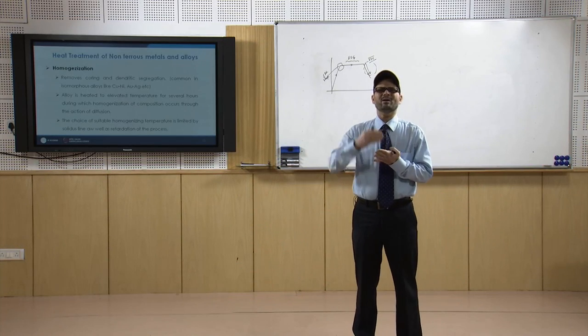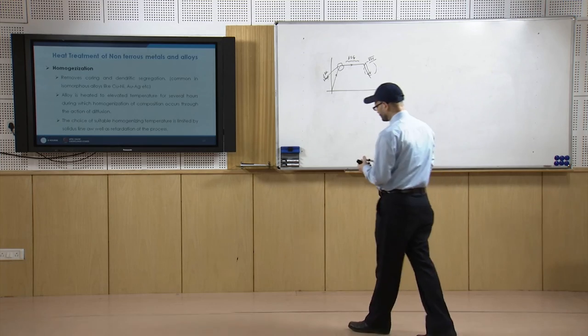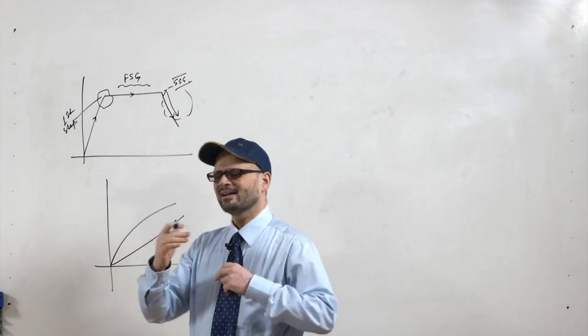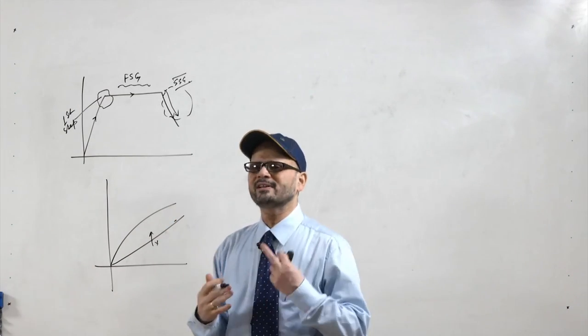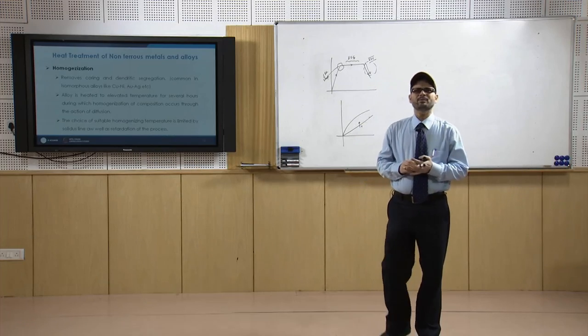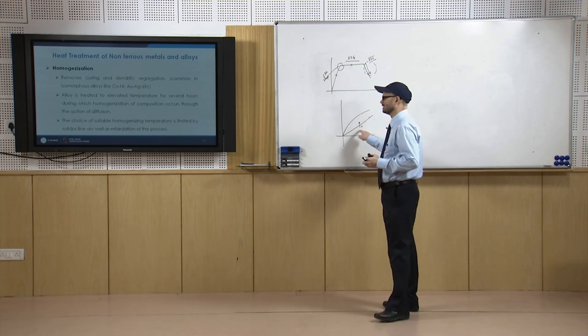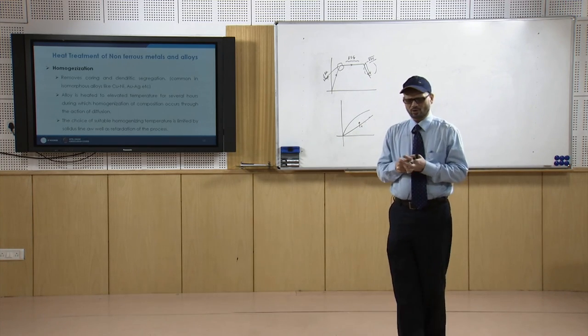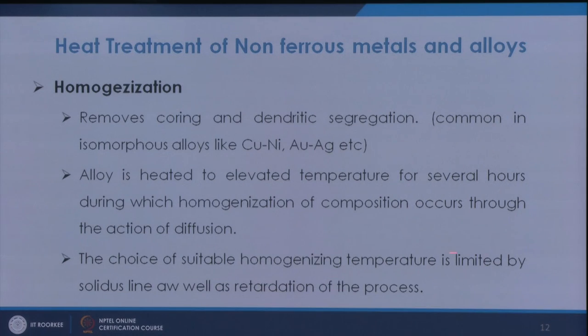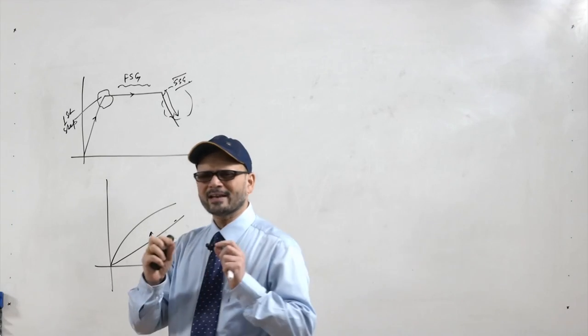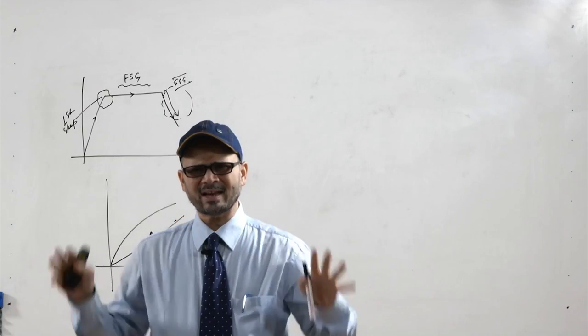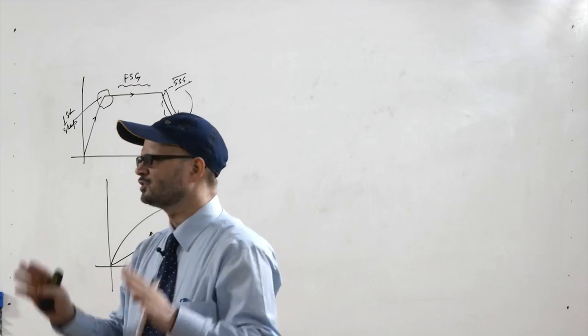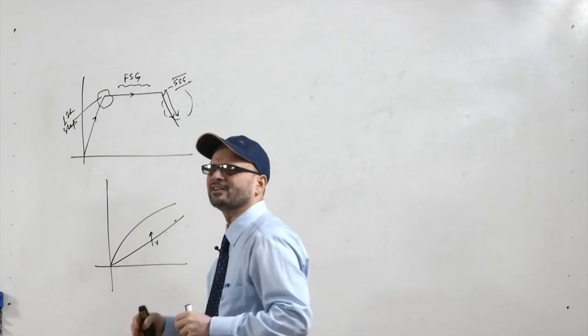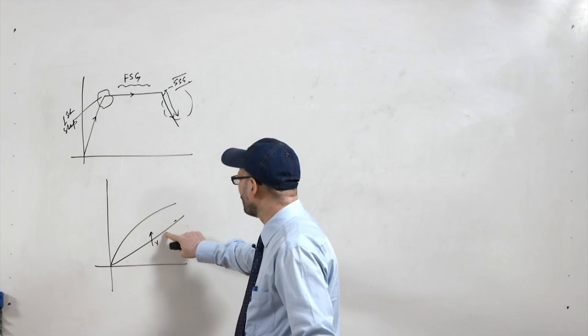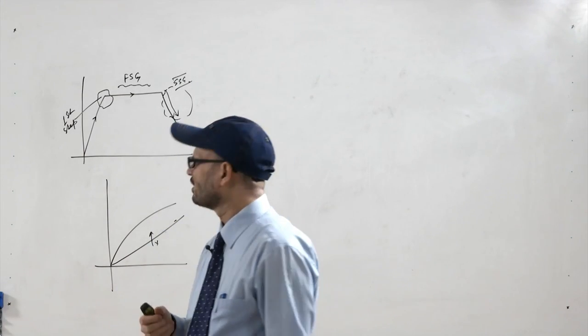So, we cannot go above a certain temperature, because if you have a solidus range, you cannot go above this, because then melting will take place. And if you go too much below this, then at lower temperature there may be less rate of diffusion. So, that is why it is written that a suitable temperature has to be taken, so that it is high enough that there is quite a good degree of diffusion taking place, so that the composition is homogenized. It is by the diffusion process that the composition is homogeneous, and the diffusion rate is somewhat higher, and it should not go beyond this line, because then there will be melting of one of the phases. So, that should be avoided.